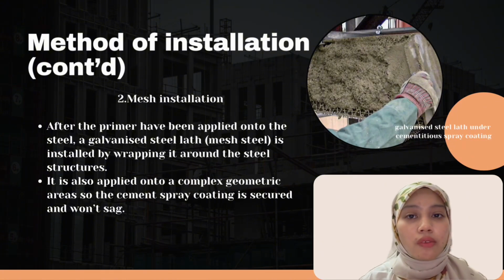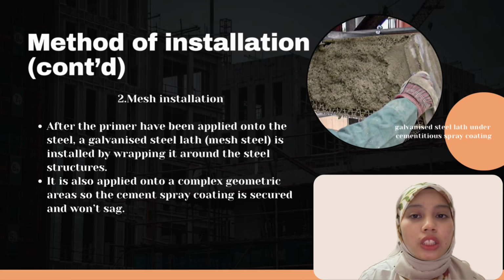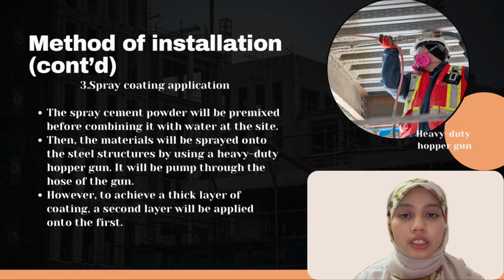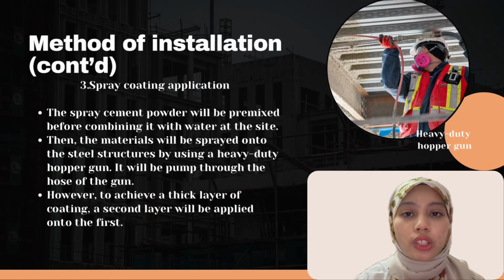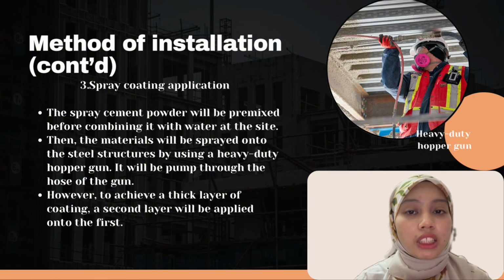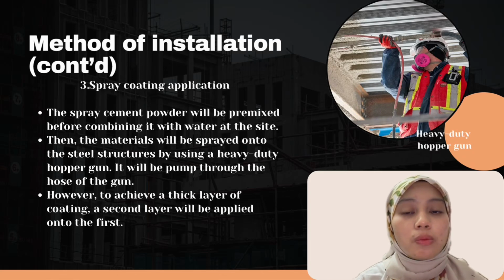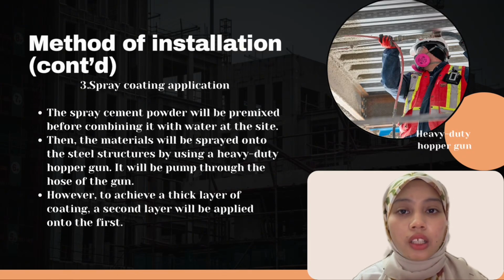A steel mesh or a galvanized steel lath is installed by wrapping it around the steel connection so the cementitious spray coating can be secure. Next is the step of applying the cementitious spray coating on the steel connections. The cementitious powder will be premixed before mixing it with water on site. Then the application starts. The spray process will use a specialized heavy-duty hopper gun. It will be pumped through the hose of the gun onto the steel connections.